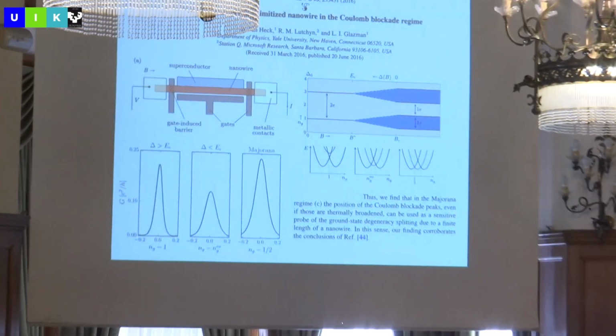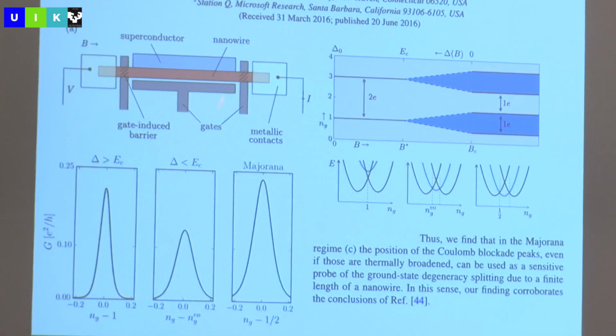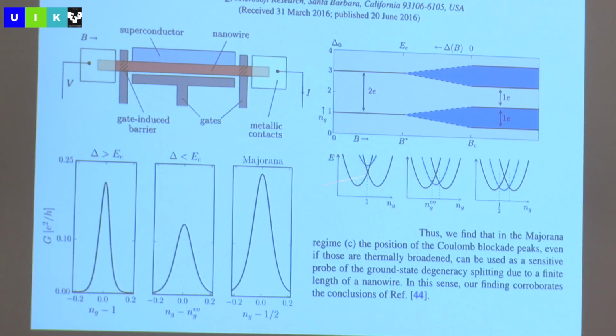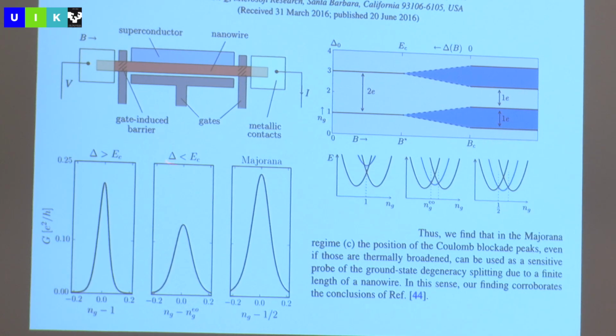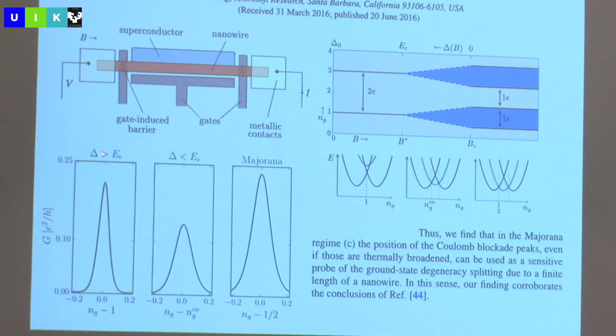Now, of course, the next thing that happens is the theory papers start to come out saying, well, we thought about this experiment and we made the quantum dot and we put this thing in and we see how the levels go down and we see how the Coulomb blockade peaks go. And when it's less than delta, you get this kind of a peak, and when it's a Majorana, you get that kind of a peak, and it should go up, then down, then up, and the brightness should go down, et cetera. And it's the next chapter.